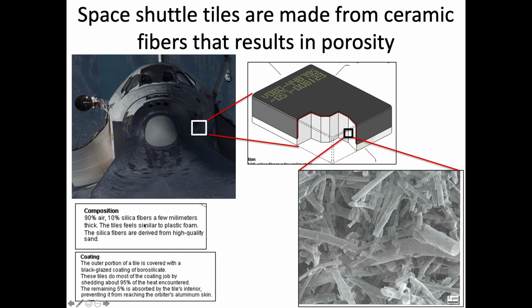Those fibers are typically silica or some other ceramic that are only a few microns or millimeters in dimension. And they're put in such a way that leaves a lot of porosity around them. If we just put those fibers together, they're not going to fill space very efficiently, so most of it, 90% of it, will be air. Air is a good thermal insulator, and so that is very good for thermal protection in space shuttles and various applications like that. So creating fibers and other materials like that is another way that we can create these porous materials. That's not all of the different ways, but that is some of the ways in which we can make porous materials, keeping in mind that we've talked a lot about dense ceramics, but there are a lot of applications for porous ceramics as well.